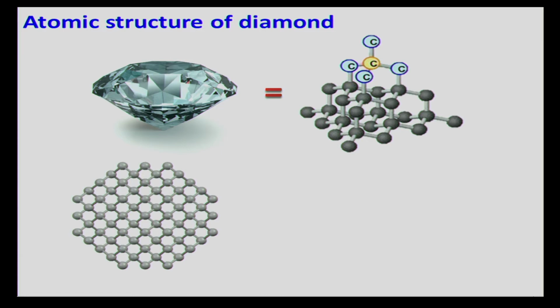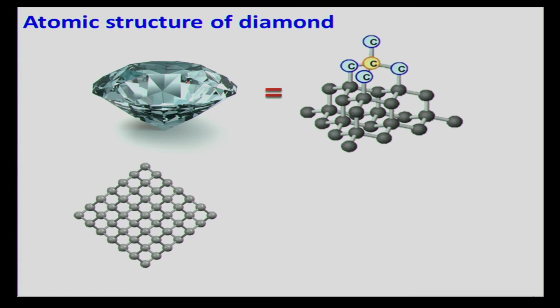And if we take that and we project it onto a two-dimensional plane, this is what we have. Now you can start to see that there are edge atoms, and there are, let's say, bulk atoms or central atoms. Now what I want to do is take these edge atoms one layer at a time, and as I do that, I'm shrinking the size of this, let's say, chunk of diamond. And as you do that, you can imagine some of these carbons that were originally in the bulk or in the center are now exposed to the edge.